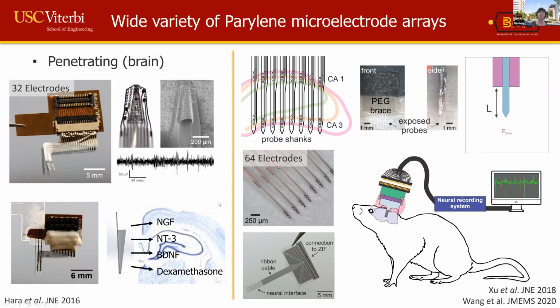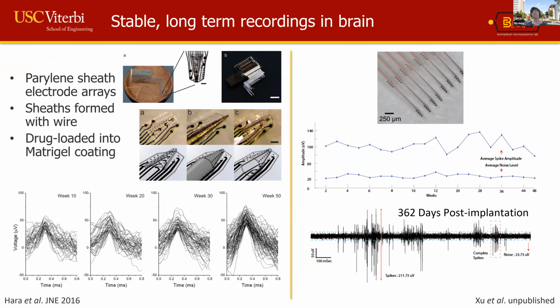And this is in contrast to the prior approach on the left-hand side over here, where we're using insertion tools that actually do add a bit of bulk to the system and do more damage. So with both of these, I want to stress that we're able to get long-term recordings. And so I took a snapshot of data that we took, roughly a year out for both of these devices. And we're able to get stable long-term recordings in the brain with both of them. And so that's a significant improvement over some of the silicon-based devices where you can get weeks, maybe a couple of months, but it's difficult to have great longevity of electrode sites over years.